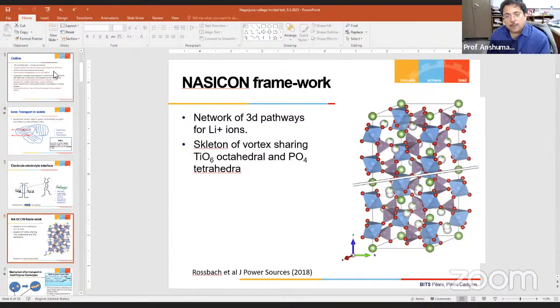All right. So you talk about such kind of skeletons which should be prepared. For example, this titanium octahedra and phosphate tetrahedra, when they are joining at the corners, then there is a lot of free space inside. And this is a three-dimensional tunnel-like structure. And now it is possible to think about such a three-dimensional tunnel-like structure in lithium systems also. In garnets also a very similar thing happens whenever the tetrahedra and octahedra share the corners rather than sharing the faces. Then we are able to achieve space inside the solid, and using that space, ionic transport is possible.